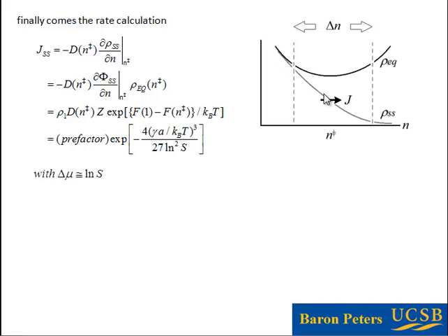This is the steady state distribution, and it's a rather inconvenient thing to work with. We prefer to think about this equilibrium distribution because, of course, it has this nice physical interpretation just in terms of the interfacial free energy and driving force parameters that we saw in a previous talk. Okay, so this is the equilibrium population of nuclei as a function of nucleus size here, and you see that it passes through a minimum. This is the rarest of all nuclei, right there at n double dagger. This is my critical nucleus size, and it really doesn't enter into this picture at all, right?